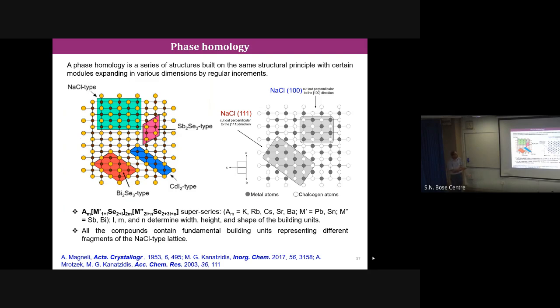So this is the NaCl type of structure, one cut of NaCl. So this is the NaCl structure. If I cut like this it becomes Sb2Se3 structure. If I cut like this, it becomes CdI2 structure. If I cut like this, it becomes Bismuth Bi2Se3 structure, right? So now if I combine this Bi2Se3 structure and CdI2 structure on top of one another, I can create a new compound, right? If I have two CdI2 to one Bismuth selenide, then I have another new compound. So if I generate a formula out of it, this is compound generating. So these are called homologous compounds.